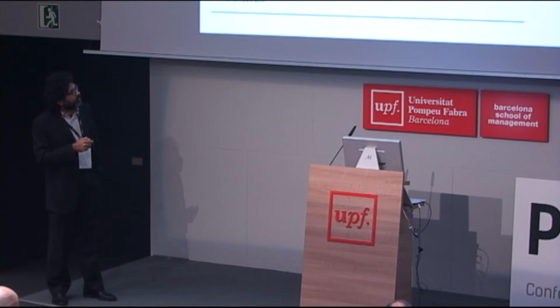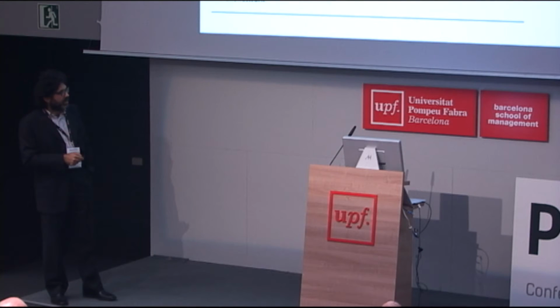If you look at the optical density of the system composed of nanowires plus nanoparticles compared to nanowires alone, you see a significant increase in absorption, and this reflects directly on the short circuit photocurrent density in our solar cell, and in the efficiency, which is almost 3 times higher than with just nanowires. This kind of efficiency is pretty low because of the thickness of the nanowires.